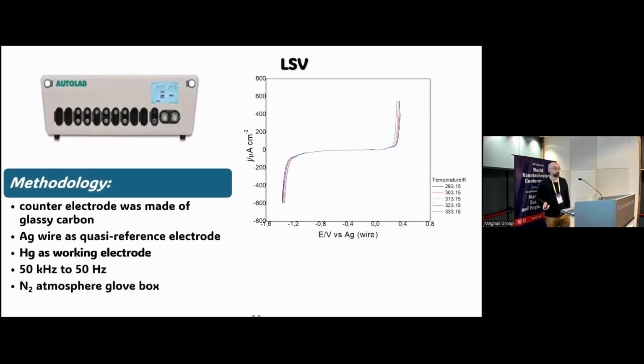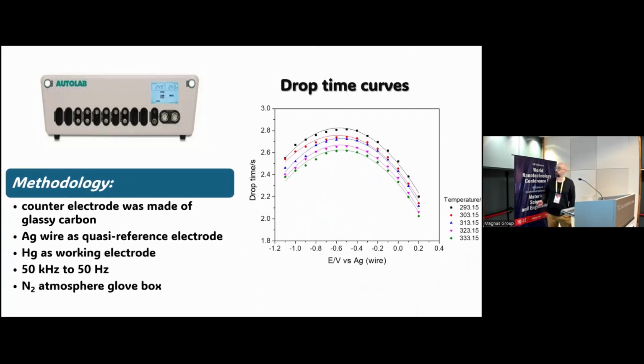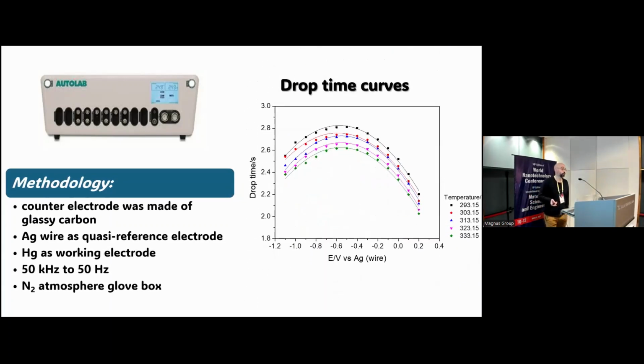We have also performed the linear sweep voltammetry of our compound. In this case, we have used a counter electrode of glassy carbon, silver wire as quasi-reference electrode, and mercury as working electrode. You can see that practically there is no difference with temperature in our linear sweep voltammetry of the pure compound. Then we move to the potential of zero charge, quite important in the next slide to determine the density and the energy density of our compound.